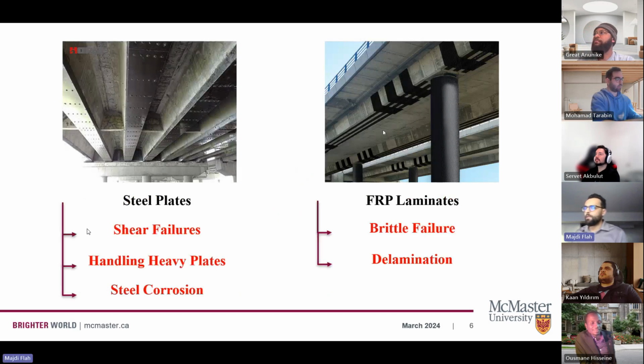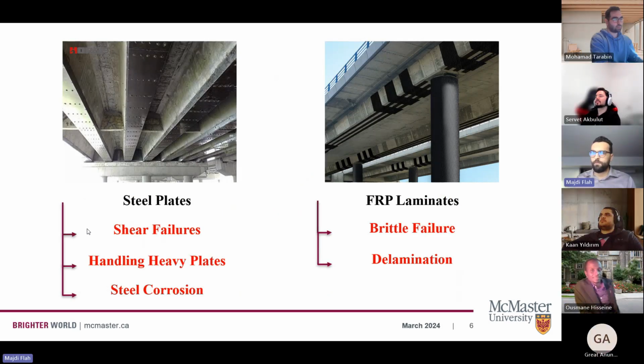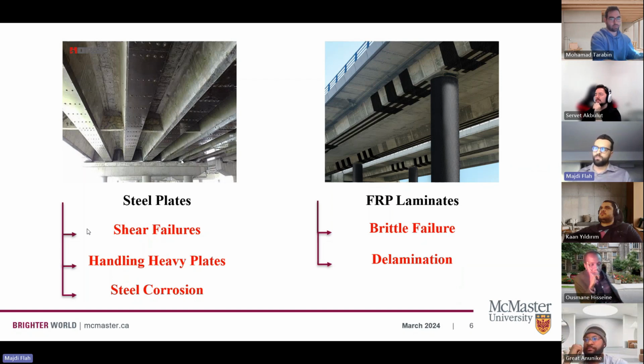So currently, the practice is to repair our infrastructure using steel plates or fiber reinforced laminates. However, despite being successful for a limited time, there are a lot of limitations concerning the shear failures, for example, for the steel plates, and the steel by itself is corrosive. For the fiber reinforced polymer laminates, it's a difference in the behavior of the material, because the carbon fiber and the cement don't adapt in terms of, for example, modulus of elasticity and all of that. So we're going to end up having a lot of delaminations and a lot of brittle failures,